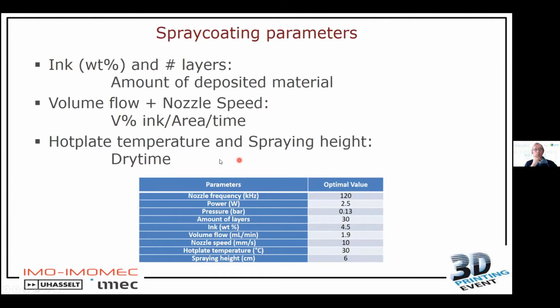Here you see the parameters of the spray coater. You have the frequency of the nozzle, which is fixed at 120 kilohertz. Then the power, 2.5 watts, that's the power you apply to generate your droplet. The pressure is what we use to focus our droplets towards the substrate, that is, the pressure applied to the nitrogen gas. As you can see, this is very, very small, and that has a specific reason. Then we put 30 layers, and we have a weight percentage of our PVDF in acetone of 4.5%. Then we play with the volume flow, the nozzle speed, the hot plate temperature, and also the height between the nozzle and the substrate.